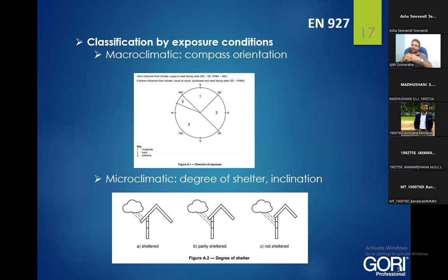I have taken this diagram here from EN927, but sometimes I feel that in Sri Lanka, because we are not like Europe, the sun is directly over us. So in that case, sometimes the south is not as risky as mentioned here, in my experience, but I'm not going to challenge the code. But in my experience, west and east are the most significant directions which we have to consider in the local industry. North is very low and south is higher than north. This is the detail provided in EN927, but anyway, we have to consider this orientation because, let's say our application faces west, then definitely it will be at high risk of degrading by UV attacks,